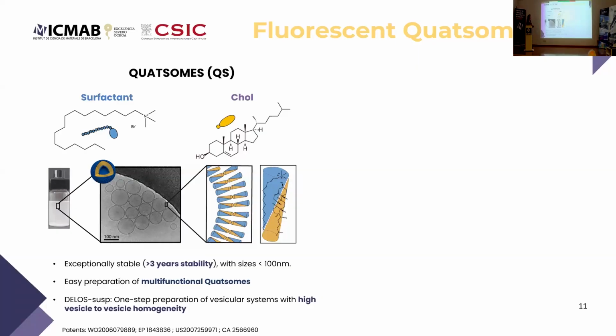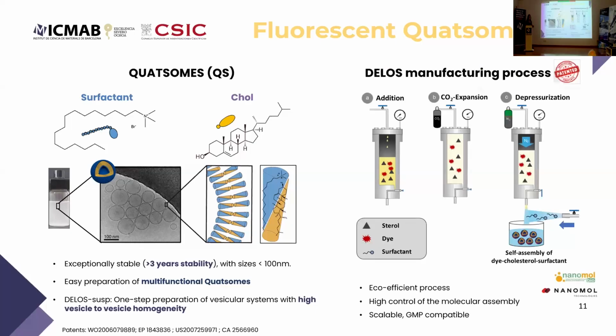So in here, we exploited quatsomes, which are small unilamellar vesicles of about 100 nanometers composed of a surfactant and a cholesterol, forming this synthon. Those quatsomes can be designed to be multifunctional, and they are prepared by the Delos manufacturing process, which is an eco-efficient process since it uses compressed CO2 as a solvent, and it allows a high control of the